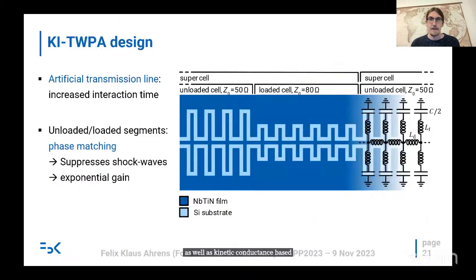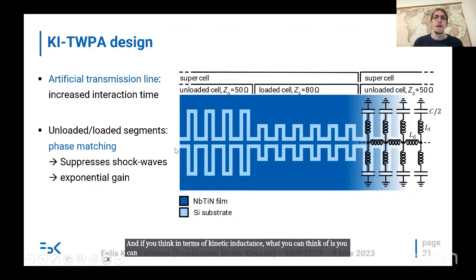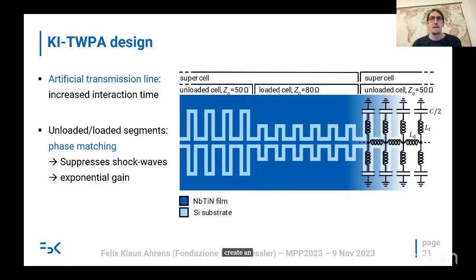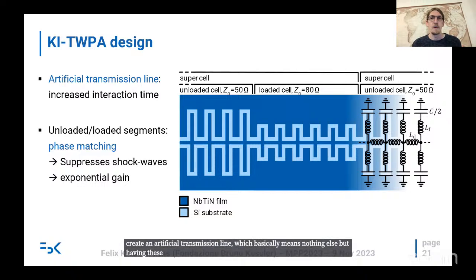There are both Josephson junction based traveling wave parametric amplifiers as well as kinetic inductance based traveling wave parametric amplifiers. If you think in terms of kinetic inductance, you can make a coplanar waveguide where in the center you have a central line, you have your ground planes around, and then you have these stubs that modulate your line and create an artificial transmission line, which basically means nothing else but that, having these stubs, you slow down your microwaves traveling through the waveguide, which increases the interaction time of the microwaves in the medium, and therefore you can enhance your amplification.